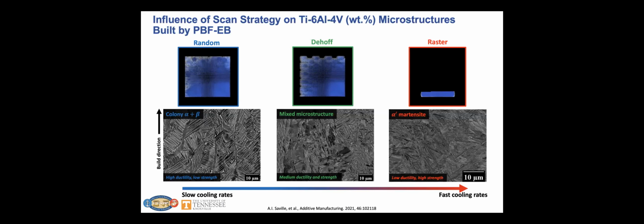So I'm going to switch gears a little bit and talk about Ti-64, which is a ubiquitous titanium alloy and the influence of scan strategy. So here we're looking at electron beam powder bed fusion for different spot melt scan strategies, our random spot melt, and then dehoff, which is kind of also a spot melt scan strategy, but kind of lies in between random and a traditional raster scan strategy.